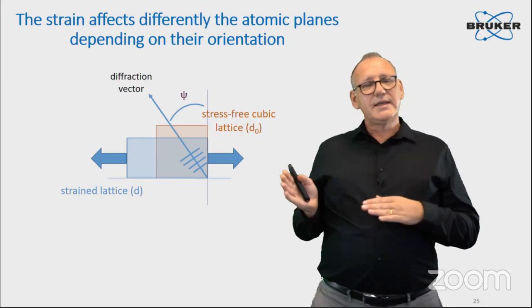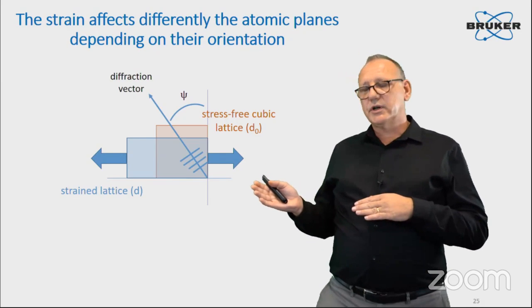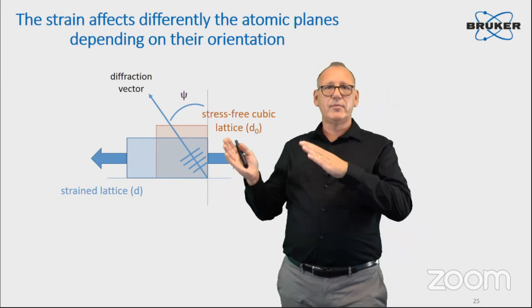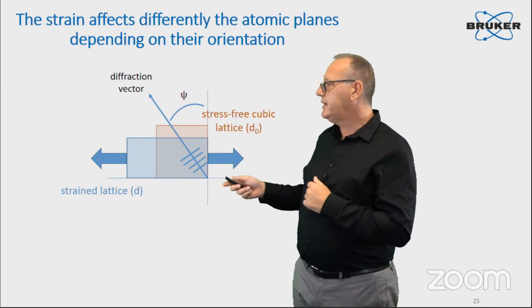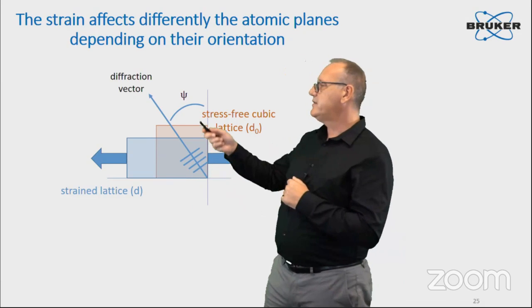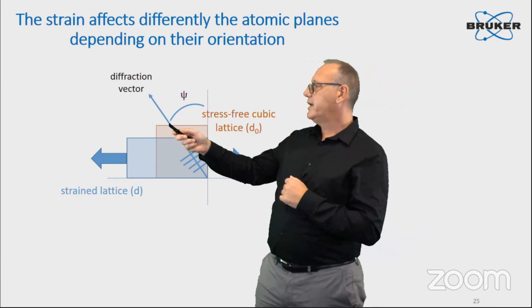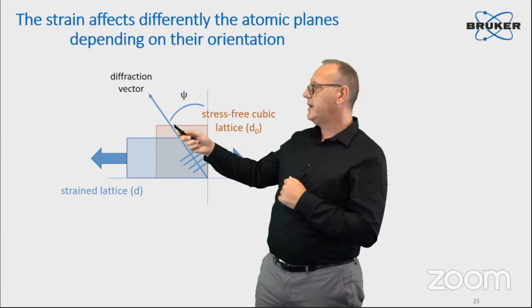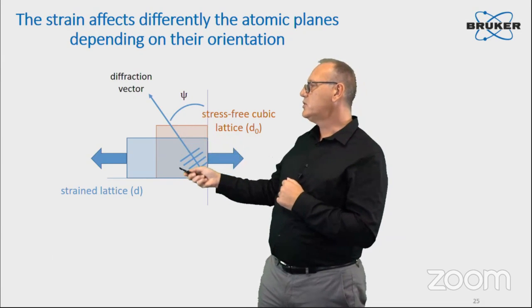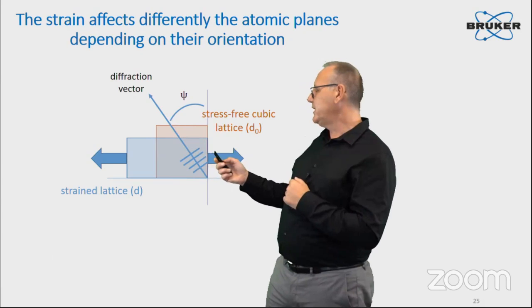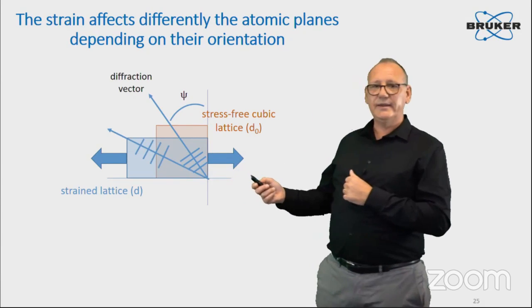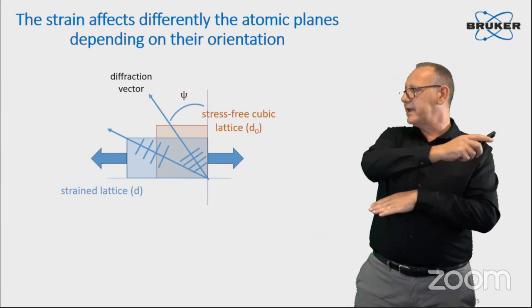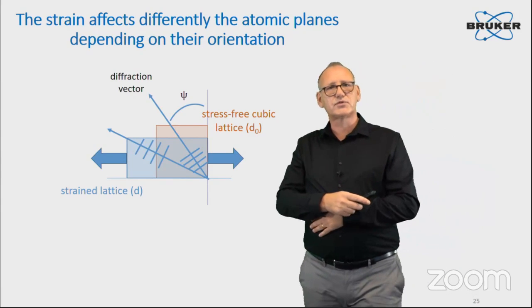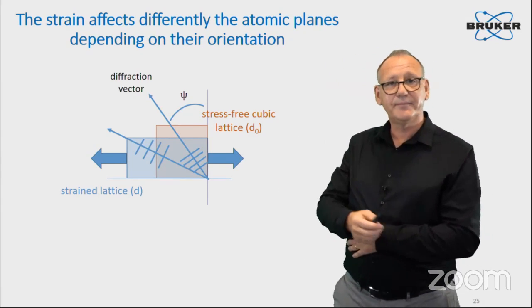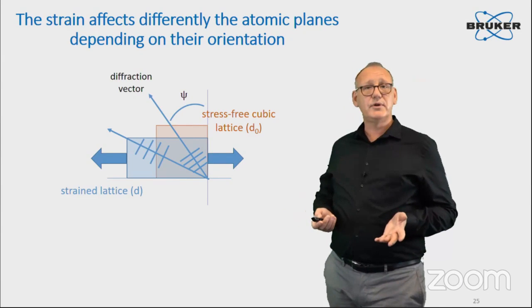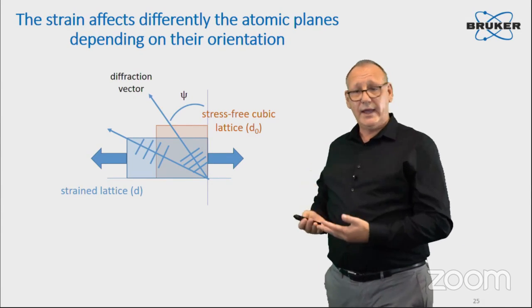You remember that grazing incidence diffraction will measure grains which have a variable inclination. And definitely those planes measured with this diffraction vector here, that we can also recognize here with a psi angle with respect to the surface normal, those planes will probably have a different strain status than those planes when we reach the end of the grazing incidence scan. So this is the origin of a strong shift if you have a high strain. And this is only possible to observe if you go to higher angle.